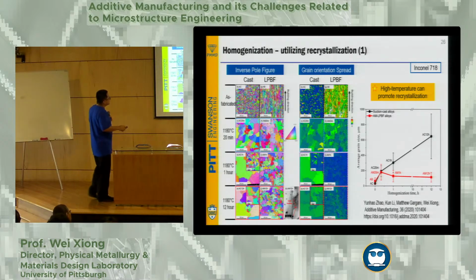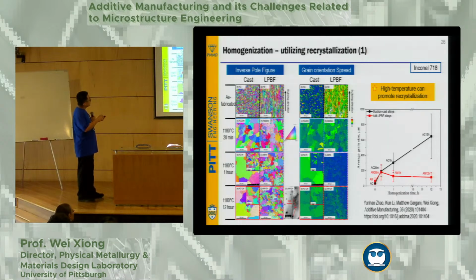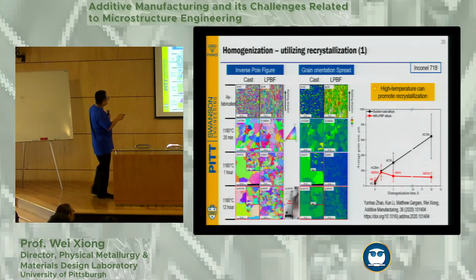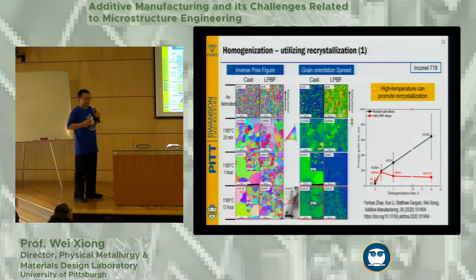So what we do with the Inconel 718, also another high temperature alloy, is compare the cast and the LPBF, this is laser powder bed fusion process. As you can see, this is the as-received microstructure with the cast. It's almost like a perfect equiaxed structure. With the LPBF method, you can see the columnar structure very much.